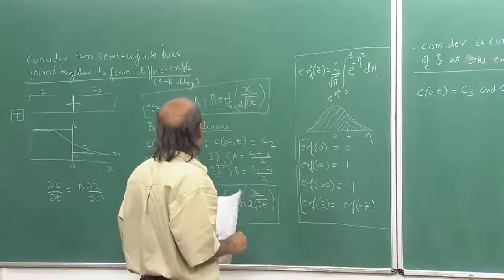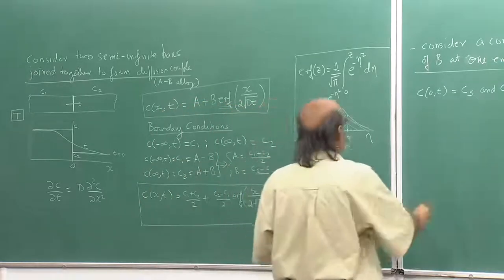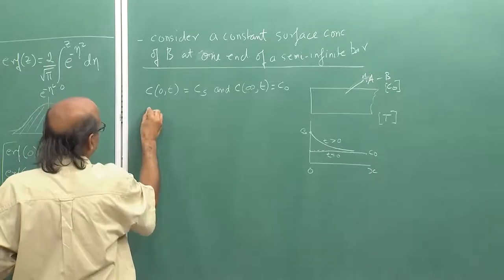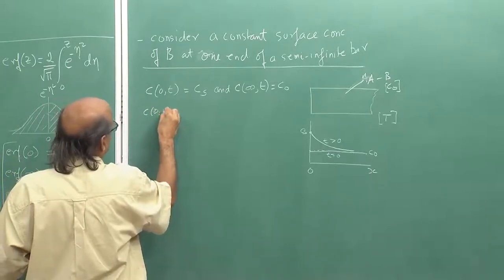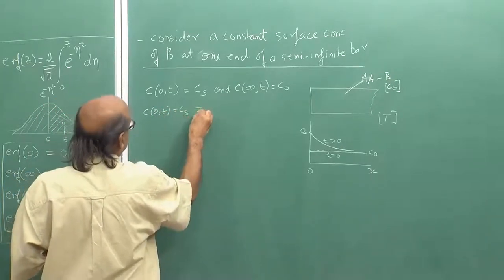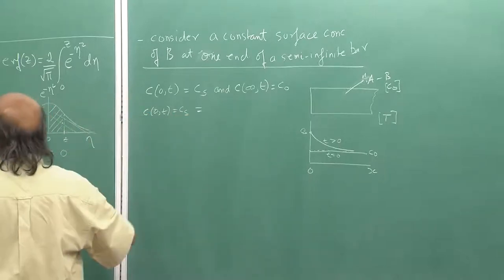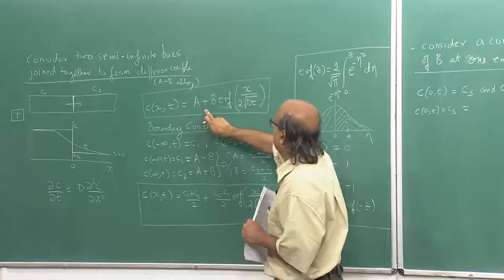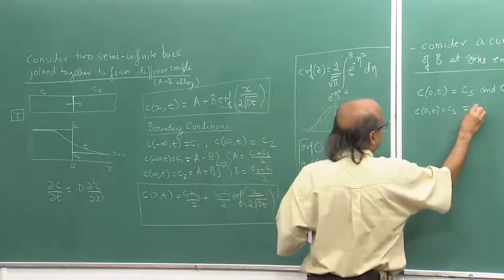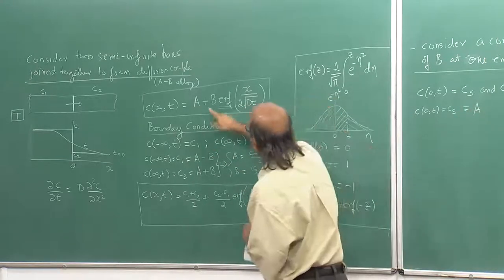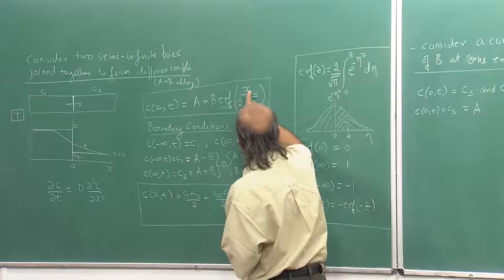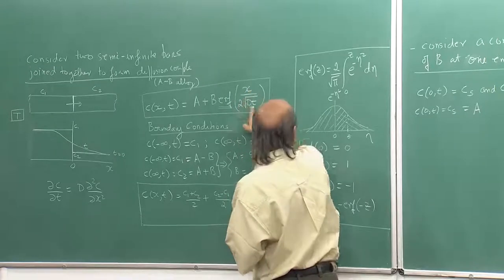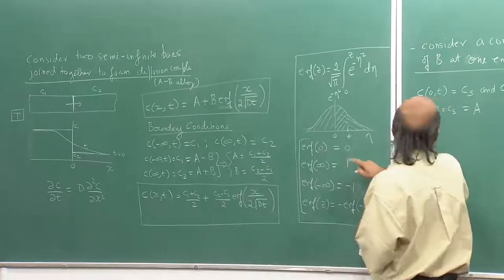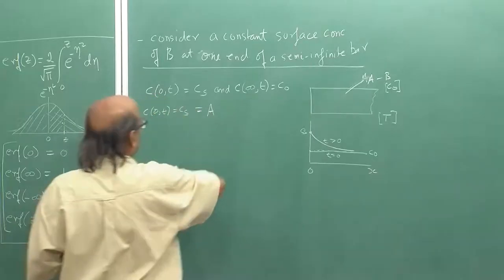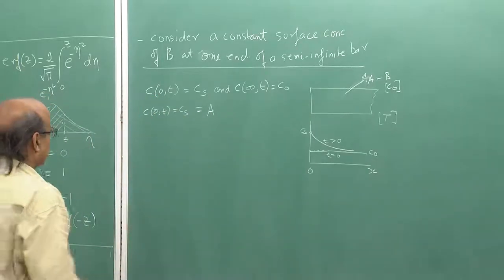Apply this boundary condition to the solution. So I will get C at x equals 0, t equals Cs, which is equal to, at x equal to 0, A plus B times error function of 0. So error function of 0 we already know is 0. Hence I get Cs is equal to A.